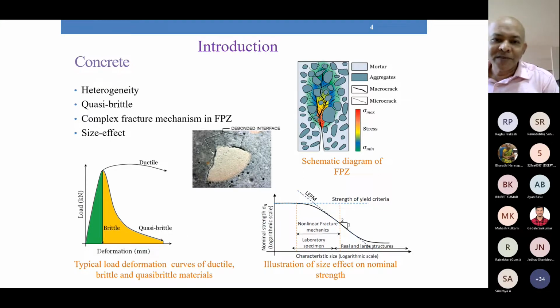And the reason why it behaves in this manner is because of the presence of a complex zone known as the fracture process zone, which is present ahead of the crack. This is analogous to the plastic zone in ductile materials. But the difference is here we have a zone containing a lot of micro cracks, and these micro cracks are around the aggregate. You can see like you have an aggregate here and you have mortar surrounding it. So there is an interfacial transition zone wherein a lot of micro cracks are present at this junction.